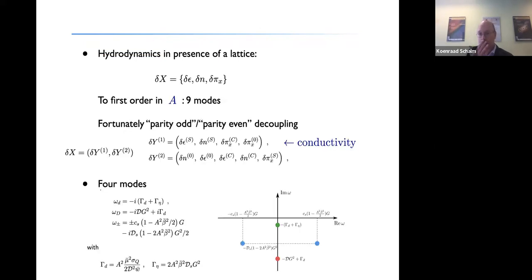you should and you can apply to hydrodynamics. So if you do this, it becomes rather complicated, because if I just look at the longitudinal sector, where I had three modes, if I do first order in the perturbation strength alpha, I now don't get three modes. The zeroth order zone has three modes, but then each of the neighboring Brillouin zones gives another three modes. So if I only limit to the first order Brillouin zones, I already have 9 modes that I have to analyze that are cross-coupled. Fortunately, there is a parity-odd, parity-even decoupling, where these 9 modes decouple in a set of 4 and a set of 5, and the longitudinal conductivity sits in this set of 4.